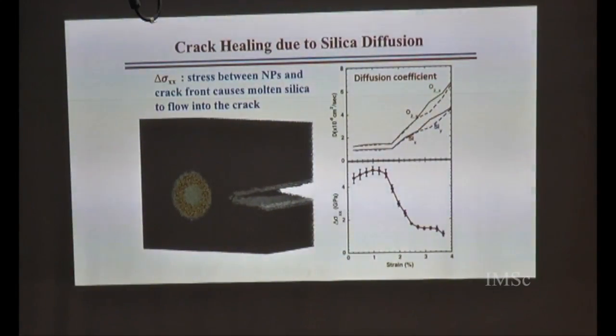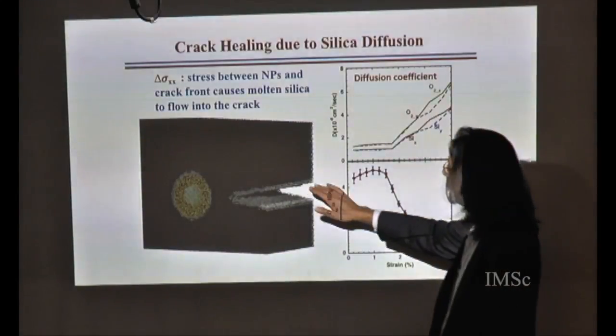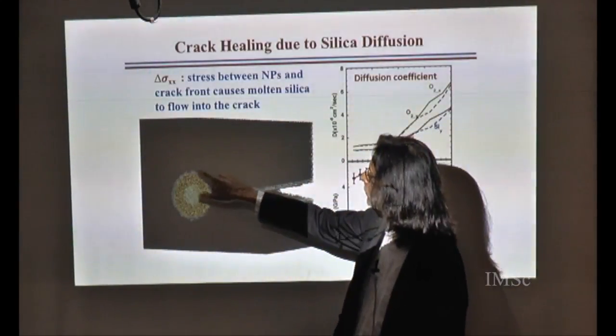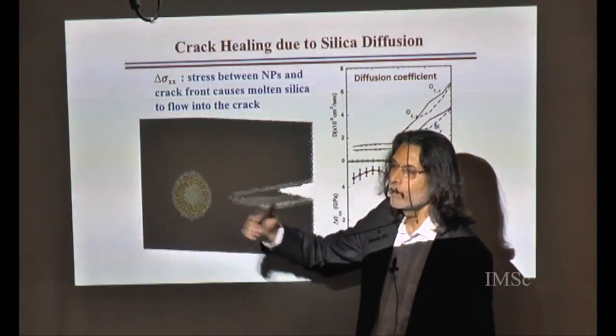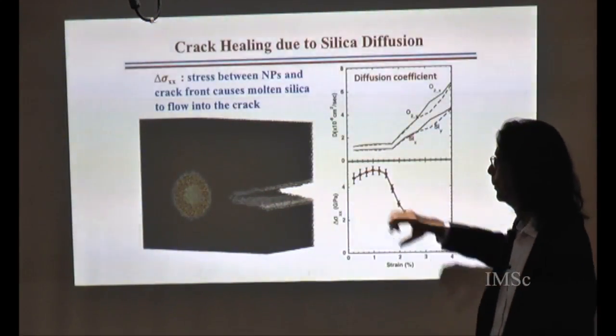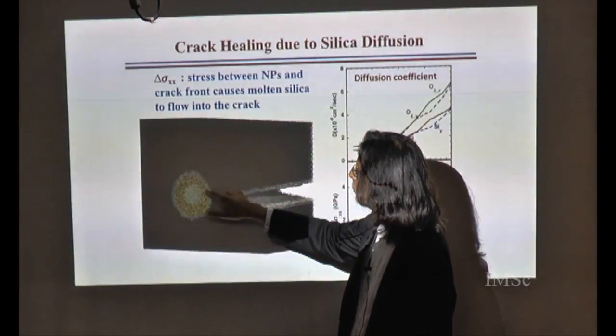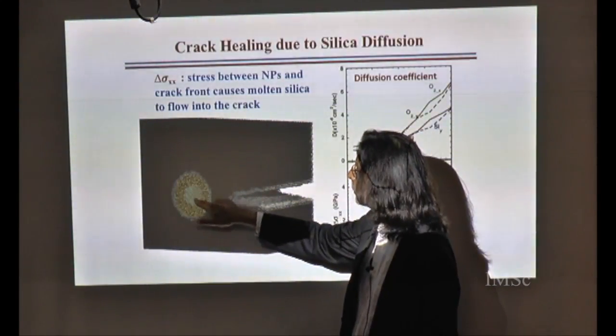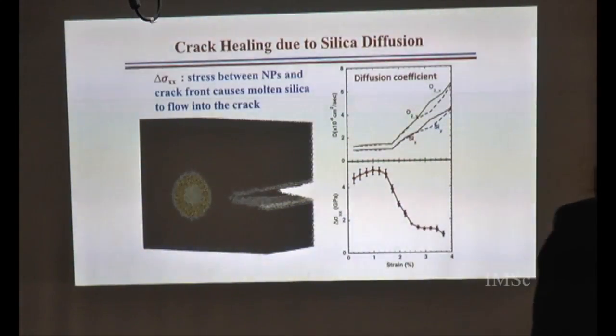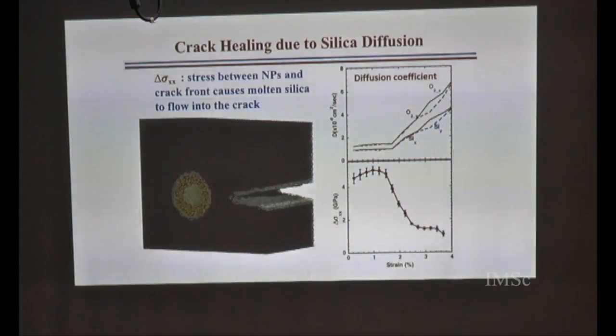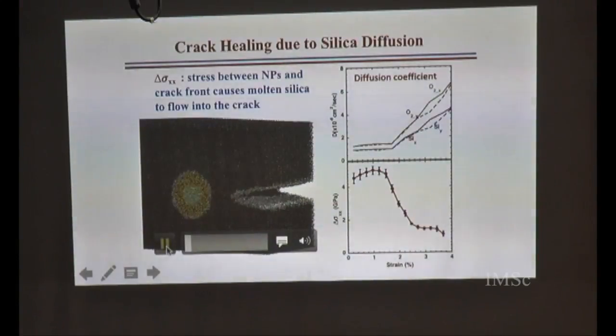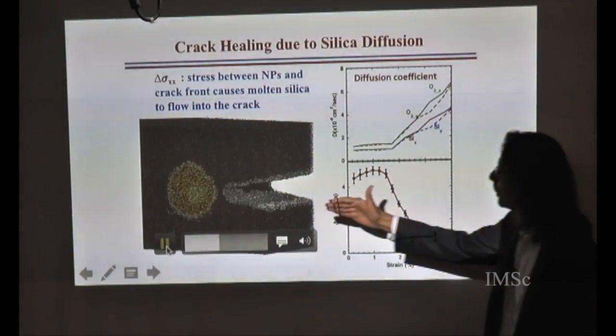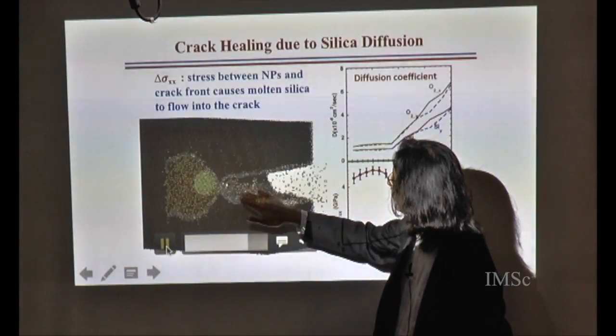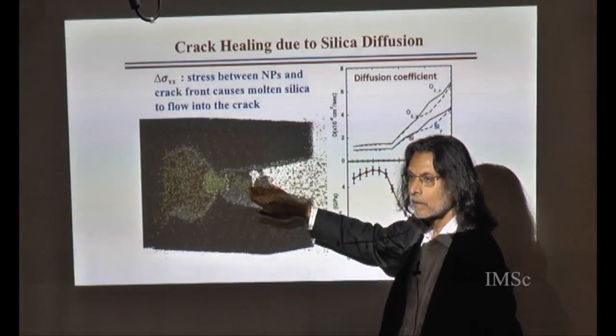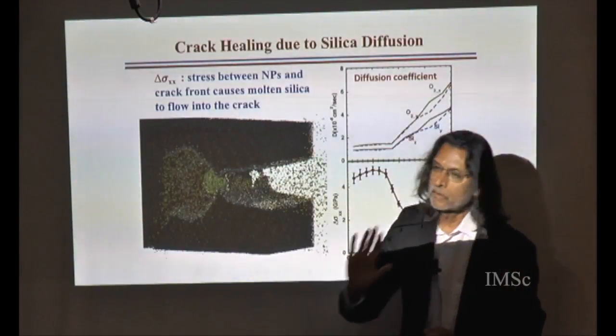I'll first show you a movie. This is the pre-crack in the system. This is a row of nanoparticles; I'm just showing you one nanoparticle in this case, but there is a row. The red and yellow here are silica, and inside is silicon carbide, which is where the healing will begin. I will run the movie. As you can see, both are approaching each other, and then you can see silica flowing into the crack in alumina, and the nanoparticle stops the crack growth.